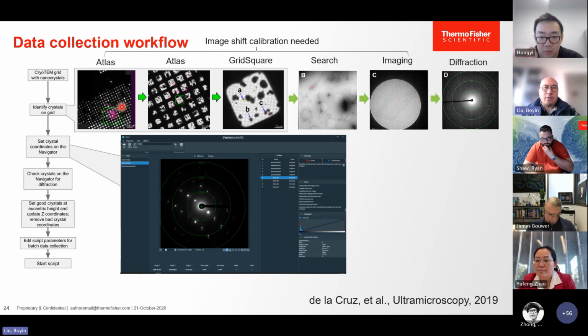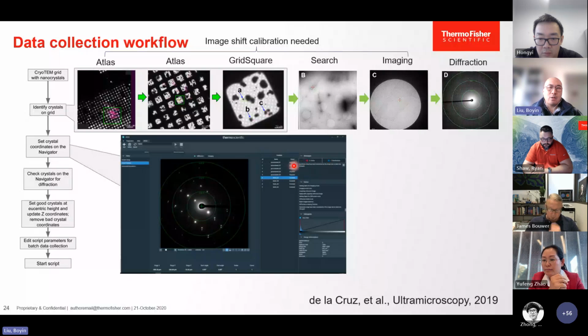the exposure. After that, EPU-D has a screening mode here on the right-hand side. It's actually a navigator. You go to the crystal, find the eucentric height, and then save the position, and EPU-D will save the X, Y, Z position for this crystal. Z position is very important. It actually saves the eucentric height for the crystal. After you press start, EPU-D will go to the crystals one by one and take one image and one diffraction image, for you to decide later which ones to throw out and which to keep. After you select the good ones, just set up your tilt strategy, and then start collecting data.